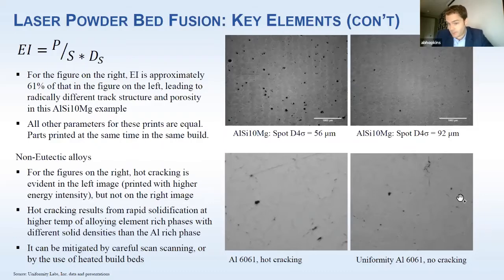If you're very careful, you can get no cracking. This is by using a different AL6061, where the melt pool doesn't heat up as much. In this case, a denser one, but also changing the scan parameters aggressively to get more rapid solidification, so that you have less time to phase separate. Another thing you can do is heat up the build bed to 300 or 400 degrees Celsius. There are only certain printers that can do that, but that helps as well.